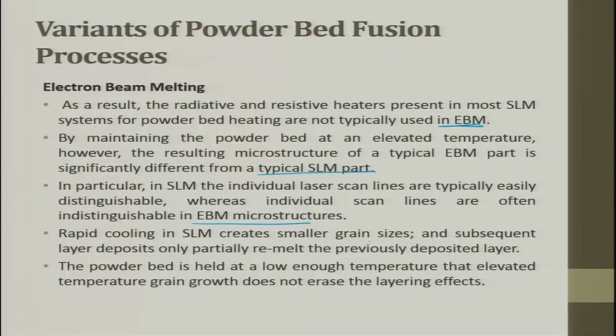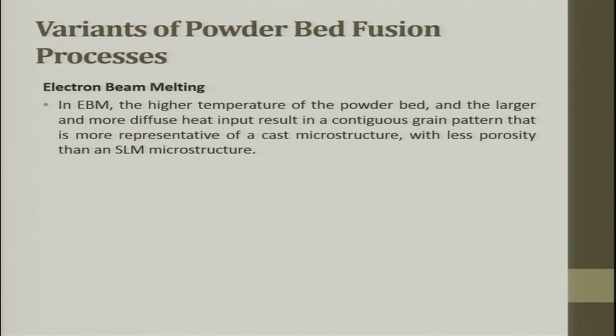Rapid cooling in SLM creates small grain size, and subsequent layer deposits only partially remelt the previously deposited layer. The powder bed is held at a low enough temperature that elevated temperature grain growth does not erase the layering effect. In electron beam, the higher temperature of the powder bed and the larger and more diffused heat input result in a contiguous grain pattern that is more representative of casting microstructure with little porosity than the SLM process. Electron beam is very advanced